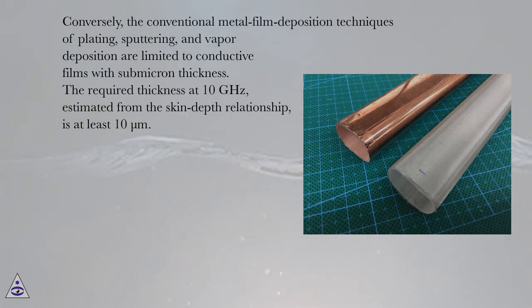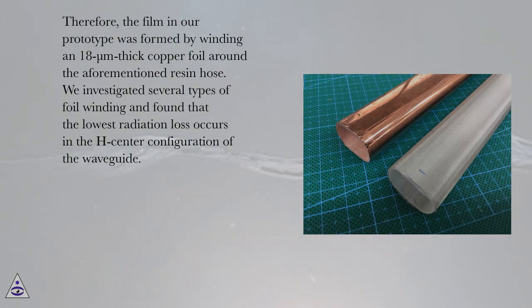Conversely, the conventional metal film deposition techniques of plating, sputtering, and vapor deposition are limited to conductive films with submicron thickness. The required thickness at 10 GHz, estimated from the skin depth relationship, is at least 10 µm. Therefore, the film in our prototype was formed by winding an 18 µm thick copper foil around the aforementioned resin